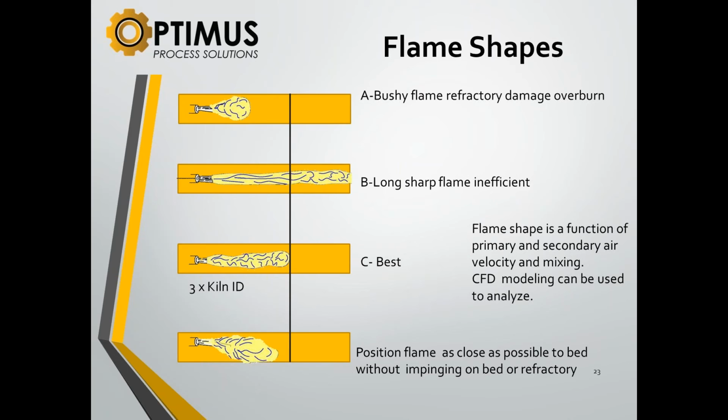So you can use a thermal camera, thermal imaging, and then see your temperature profiles. Because at the tip of the flame, it's pretty well over. You're not getting as much radiation. You're going to see that profile on the side. It won't be very distinct.